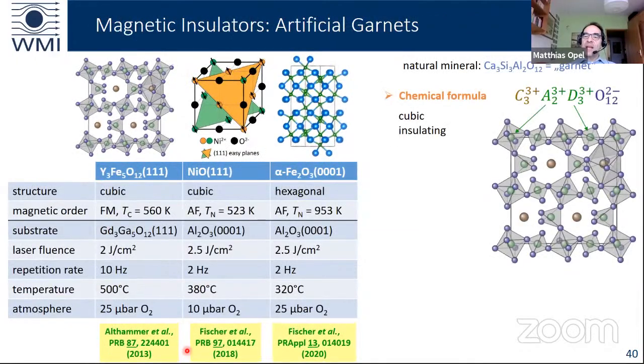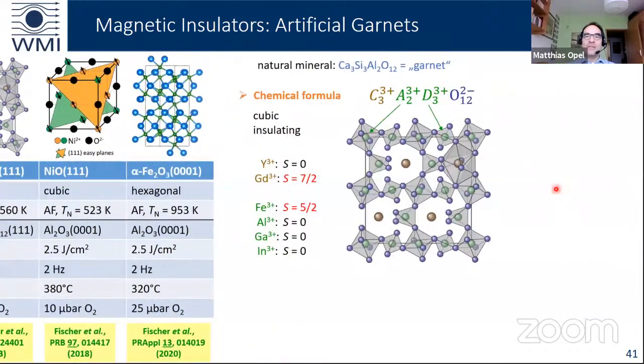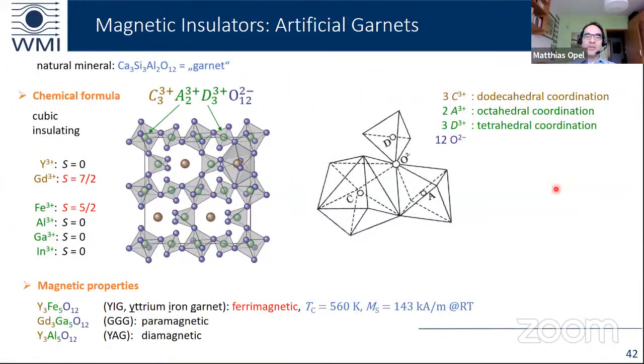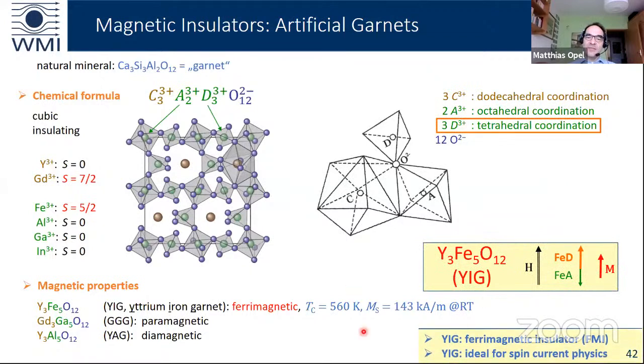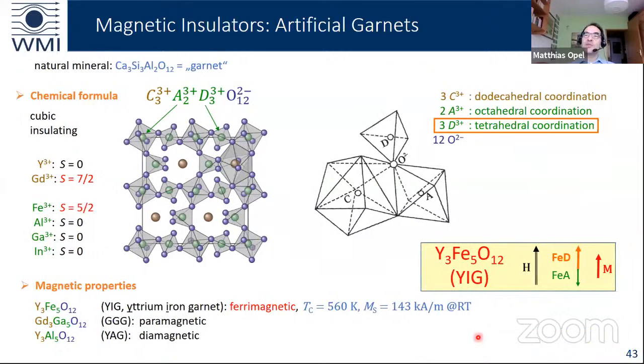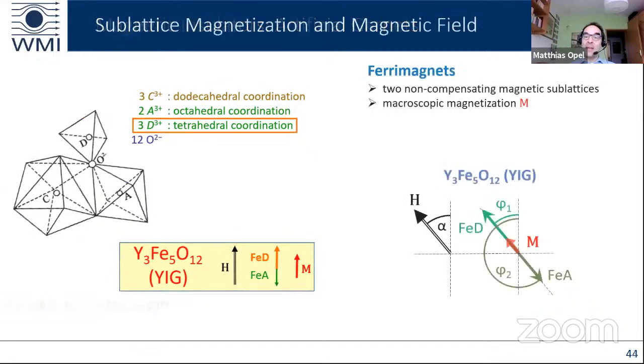So yttrium iron garnet is quite complicated. This is a view of the unit cell. This is not so important now. What is important with the yttrium iron garnet is that it is ferrimagnetic with a Curie temperature of 560 Kelvin. And because it is ferrimagnetic, it has two magnetic sublattices. So the iron D sublattice and the iron A sublattice do not compensate each other, and therefore there is a resultant net magnetization M, and this magnetization follows the external magnetic field H.